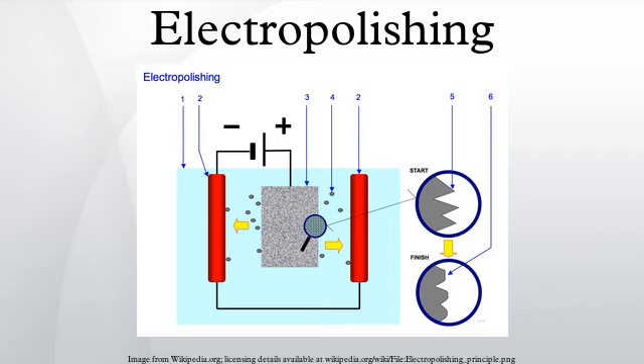than the recesses. This process, referred to as anodic leveling, is achieved by a mass transport limited dissolution reaction. Anodic dissolution under electropolishing conditions deburrs metal objects due to increased current density on corners and burrs. Most importantly, successful electropolishing should operate under diffusion limited constant current plateau, achieved by following current dependence on voltage, under constant temperature and stirring conditions.